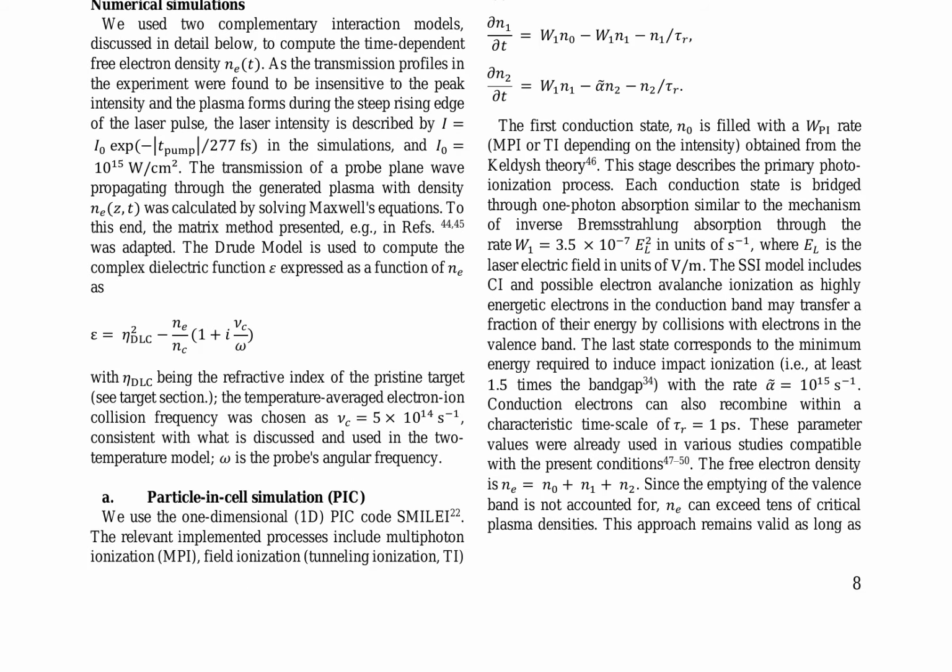The electron and ion temperatures, T_e and T_L, are described by the heat capacities C_e and C_L, respectively. The electron-ion energy exchange factor G is evaluated using the Drude model, which takes into account the electron-phonon collision frequency ν_ep. The authors also introduce a two-step interaction model, TSI, that simulates the interaction between the laser pulse and the